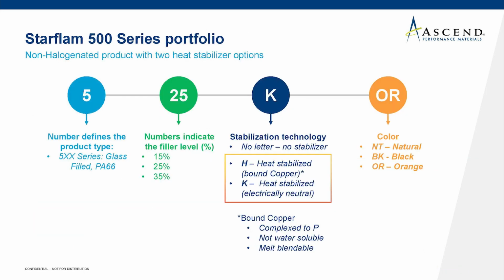Here we show the breadth of our Starflam 500 series portfolio. It's a non-halogenated product line with 2 heat stabilizer options. The 5 in the naming really just signifies glass fill PA66. The next number shows that we have a variety of different glass fiber offerings, from 15% to 25% and up to 35%.